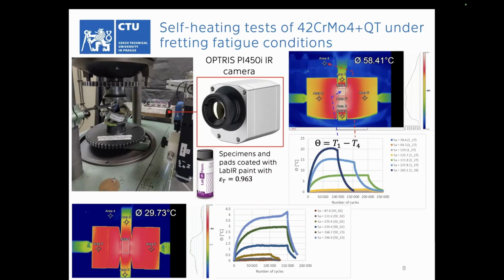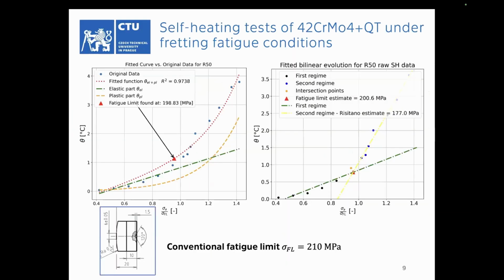Regarding the self-heating tests, we have employed the Optris infrared camera. Specimens were coated with black paint with a declared high emissivity. Here you can see some sample outputs in terms of thermographs and the temperatures in the fatigue process zone extracted from them. The stabilized temperatures from these measurements were plotted to the diagrams.